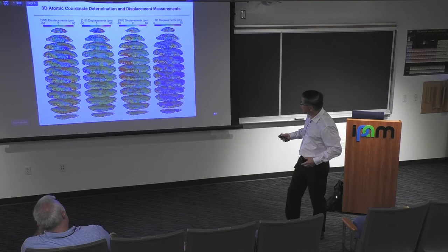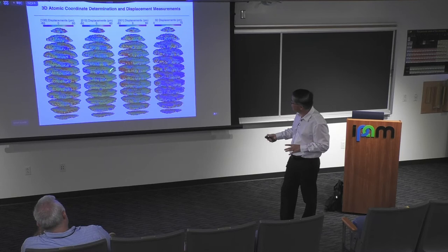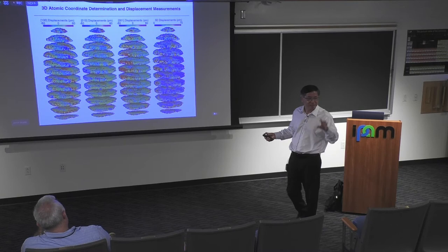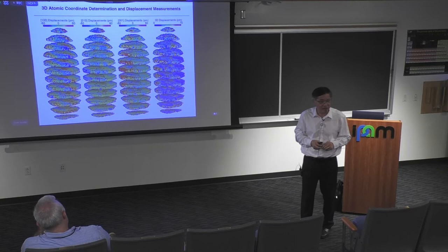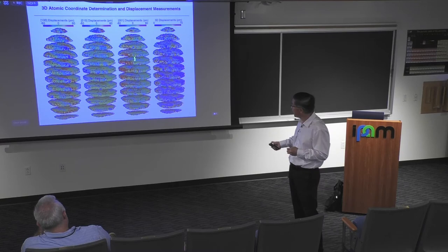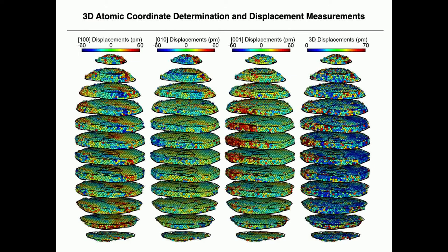And then we can identify all the atoms, truly quantitative, on different grain boundaries. And we find one surface area with some large displacement. Now I'm going to give you a quiz here. Anybody know why these surface areas actually have large displacement? It puzzled us for a few days, eventually we figured it out. Anybody want to make a guess? On this side, there's a large displacement of about 60 picometers, okay? That's 0.6 angstrom, it's small. Now 60 picometer is almost the radius, a little larger than the